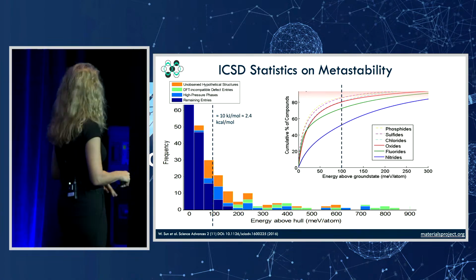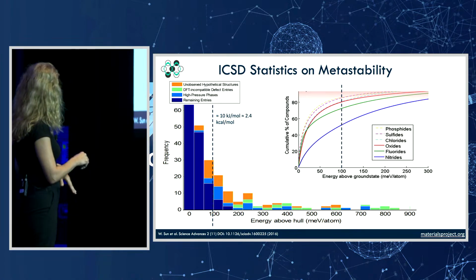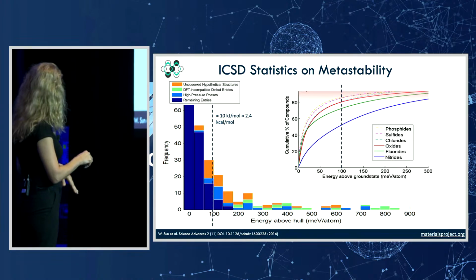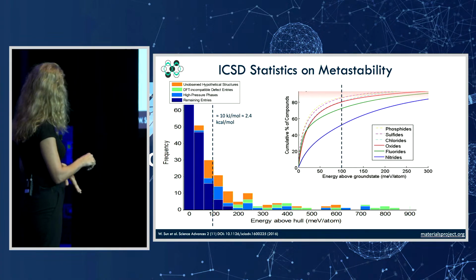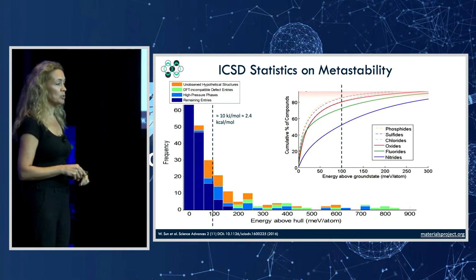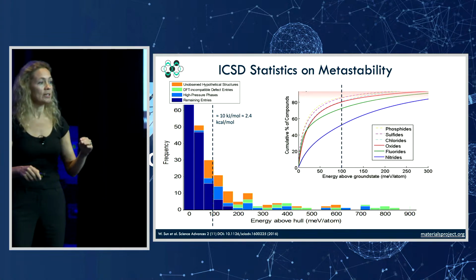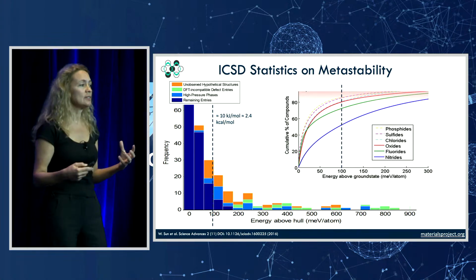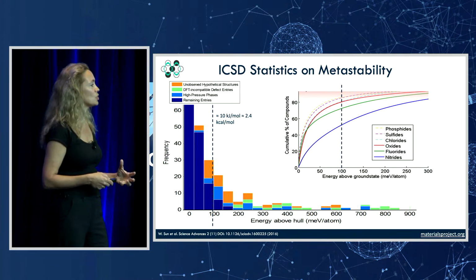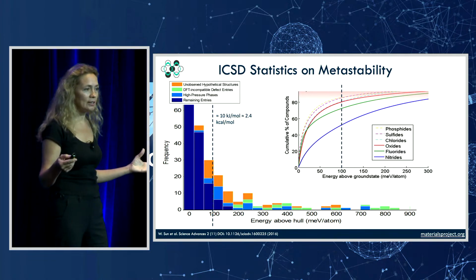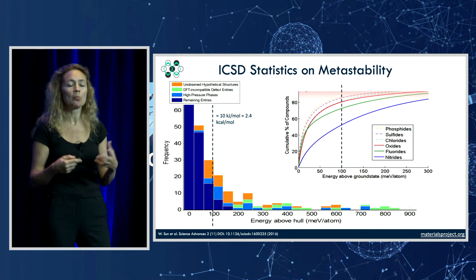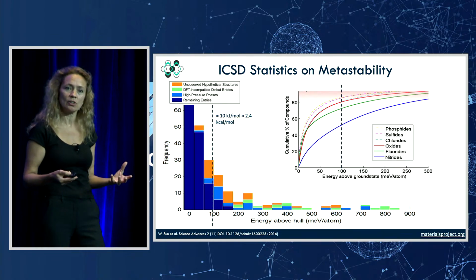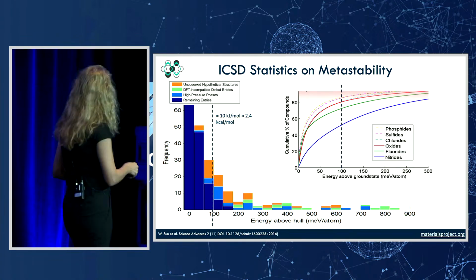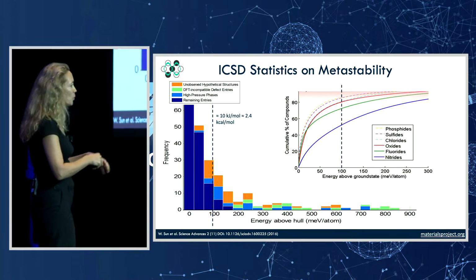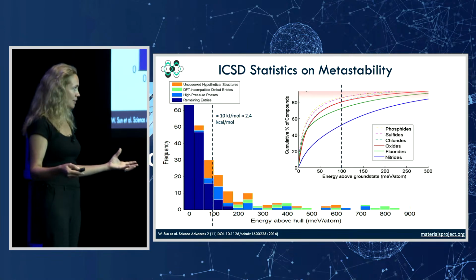Okay, that's oxides, but if we now look at other chemistries, this is the oxide line up here. You put your metric at 100 meV, you get about 80%. But if you go to nitrides, that number is only 50%. So suddenly we realize that stability or realizability, synthesizability is chemistry. Nitrides are clearly much more resistant or robust against metastability than oxides are. And we can discuss why that is, but clearly from a computational point of view, we need to be more generous in the nitride space than we are in the oxide space.